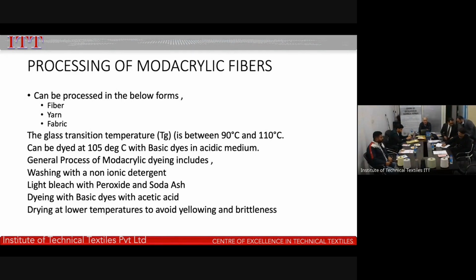Modacrylic fibers can be processed in the fiber form, yarn form, and the fabric form. The glass transition temperature is 90 to 110 degrees C, which means that they can be dyed at around 105 degrees centigrade with basic dyes in acidic medium. The general process of modacrylic dyeing will include washing with a non-ionic detergent, light bleach with peroxide and soda ash, and then dyeing with basic dyes and acetic acid. It is preferable to dry the fabric at a lower temperature to avoid yellowing and some amount of harshness primarily.